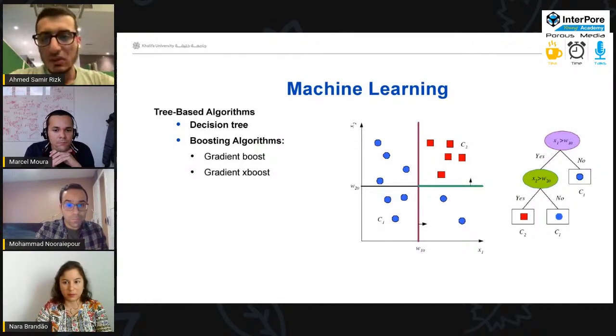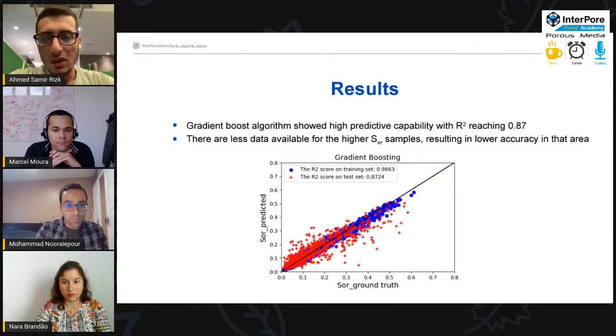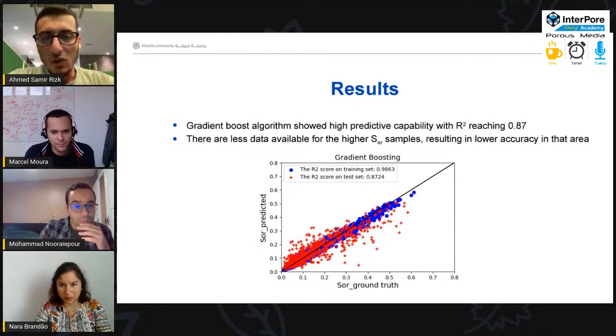In this research, we concentrated on the gradient boost method, and we trained the model on the huge amount of data we have. Then we found a very good correlation between the SOR predicted by Lattice Boltzmann and the SOR predicted by the model we developed, with around 0.98 R square in the training set and 0.87 on the testing set. Of course, if we look at the part which represents the samples with high SOR, we'll find many deviations, but this is because of the limited number of samples that have high SOR values.